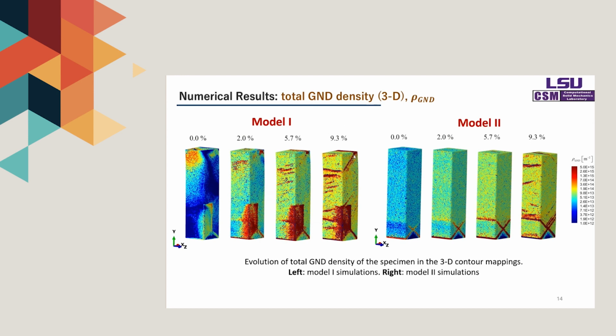On the other hand, there is no bending mode in Model 2, resulting in the barrel shape of the final configuration. Instead, the high accumulation of GND densities is expected in the primary active slip system in Model 2.